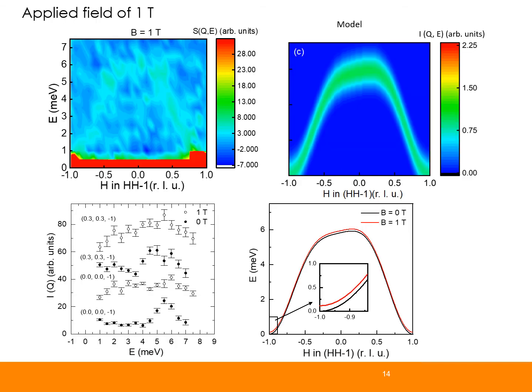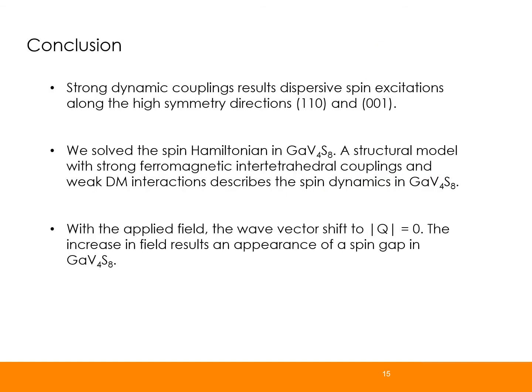To check whether the model works in field or not, we carried out some inelastic measurements in field, but due to the large background from the sample environment, it is hard to compare the zero field and magnetic field data. Although at a field of 1 Tesla, we observed that the energy scale is slightly higher compared to the zero field data. This is the outline of my talk. Even at the temperature of 2 Kelvin, we observed some finite DM interaction in the system.